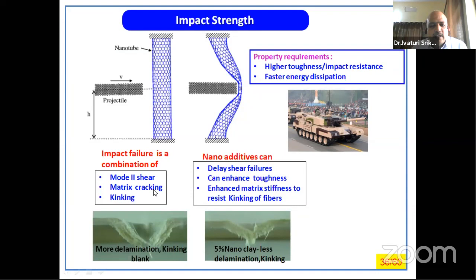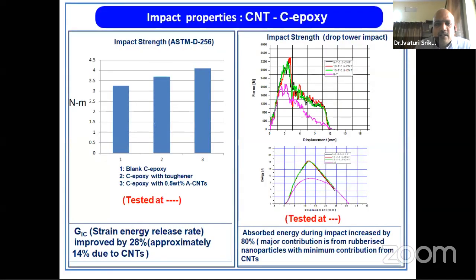And nanomaterials, by virtue of their ability to increase the shear strength, interlaminar shear strength, will increase the mode two shear resistance. And they are able to increase the strength of the matrix. As I told in one of my slides, if you add CNTs into the matrix, matrix strength will increase. So they strengthen the matrix. As the matrix is strengthened, there is an improvement in the impact and even compression properties. So there is a possibility of improving these properties by adding the nanomaterials. These studies we have done by adding nano clay, carbon nanotubes, and different other things.